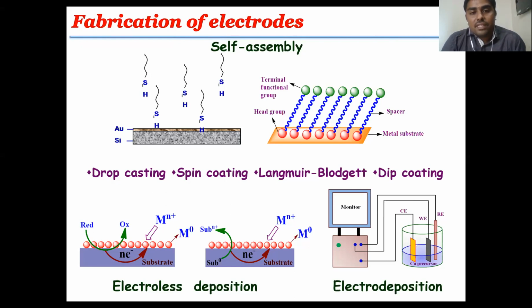In the case of self-assembly, with the support of a linker, the metal nanoparticles can be fabricated on the substrate, on the surface of the electrode substrate. The well-known alkyl thiolate gold and alkyl silane gold are the known examples for the self-assembly and fabrication of gold nanoparticles on the electrode surface.